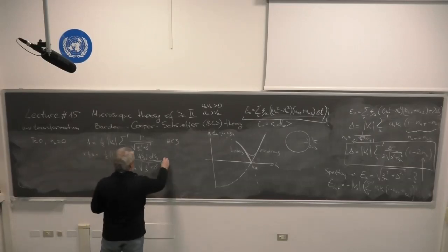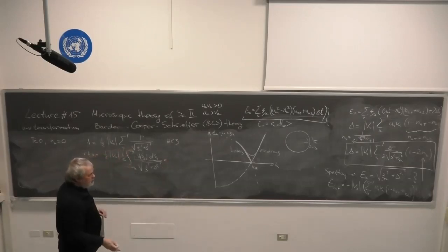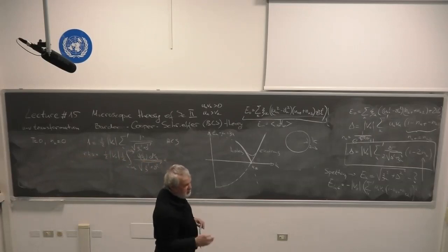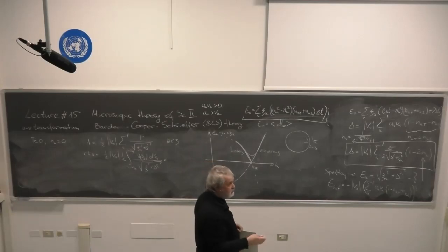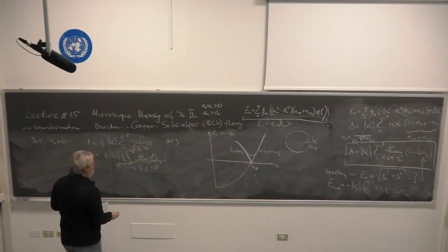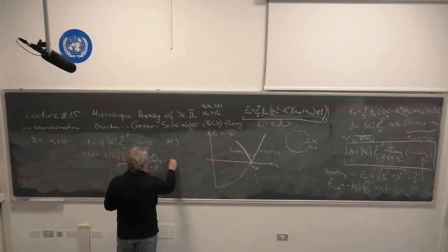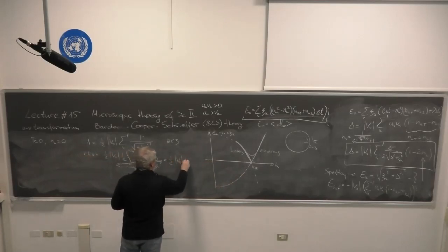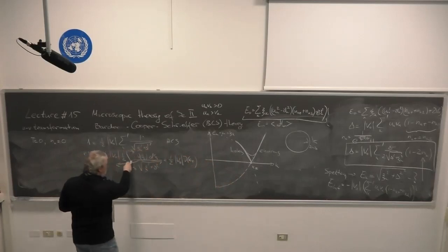Good. So we know that the Fermi energy is much larger than the Debye frequency. Typical Debye frequency is of the order of room temperature, 200-300 kelvins. The Fermi energy is 10,000 kelvins or larger. Therefore, without losing generality, I can take the density of states out and put it in front of the integral. So I have 1/2 V naught times the density of states at the Fermi level. I have two integrals, from 0 to omega d and from minus omega d to 0.